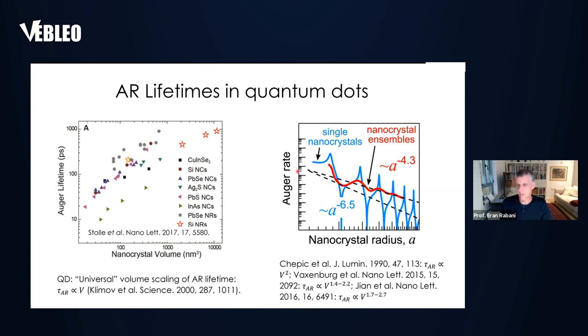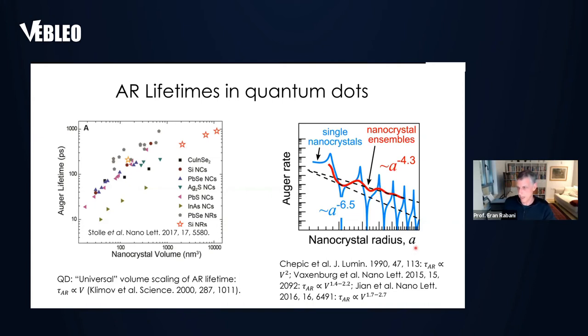The first is that the rate oscillates — it goes up and down — and doesn't behave monotonically. This was identified as resonances in the quantum-confined structure, and even if you average over an ensemble, those oscillations are present, which do not really occur in the experiment. The other, more troubling issue is that the scaling of the Auger recombination rate is way steeper than the volume scaling. If it were volume scaling with radius a, we would see a scaling of a to the minus three. But the canonical result for the non-interacting picture is that the Auger lifetime scales as V to the power of 1.4 to 2.2 — in complete disagreement with the experimental observation.